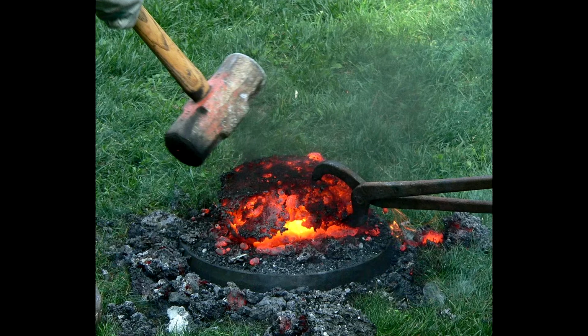That's the good news. The bad news is oxidation. We all know that iron rusts, picking up oxygen in the air to make iron oxides. At room temperature, with normal humidity, this happens slowly. At 1100 degrees Celsius, this happens very rapidly, because the high temperature encourages chemical reactions. Inside the bloomery furnace, this process was discouraged because the environment was oxygen-starved. But blacksmiths cannot work in oxygen-starved environments. They need to breathe. Citation needed. Which means our hot metal is going to begin to form a coating of oxides, rust, around it, which is called mill scale, or hammer scale, or just scale.